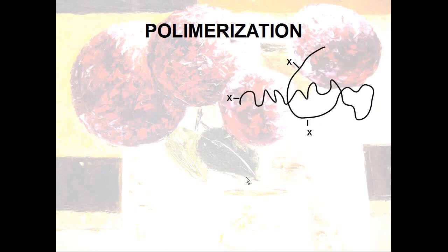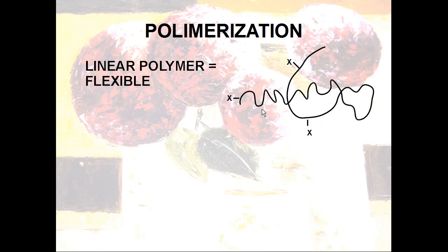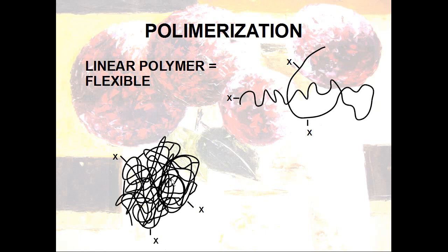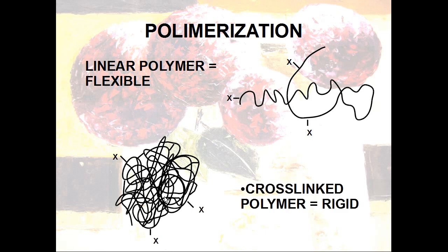Well, we can get two different kinds of chains depending on the precursor we choose. Linear chains mean soft, flexible. This is a chemistry we already know: the chemistry of silicone oil, of silicone softener. Or we can get a very reticulated, cross-linked chain. In this case, the polymer will be very rigid, hard. In the first case, we have mainly silanediol. In this case, we have mainly the 3 or the tetra substituted.